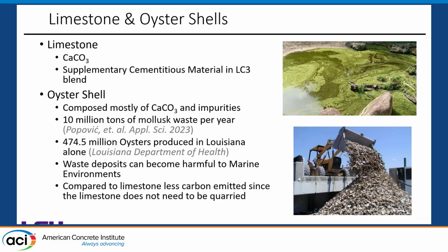The second main supplementary cementitious material used in LC3 is limestone. You can think of limestone on a chemical level as calcium carbonate, or CaCO3. And we saw a potential to make an even more environmentally friendly mix by replacing this limestone with powdered oyster shell. On a chemical level, the oyster shell is also calcium carbonate. However, it does have a bit more impurities in it.